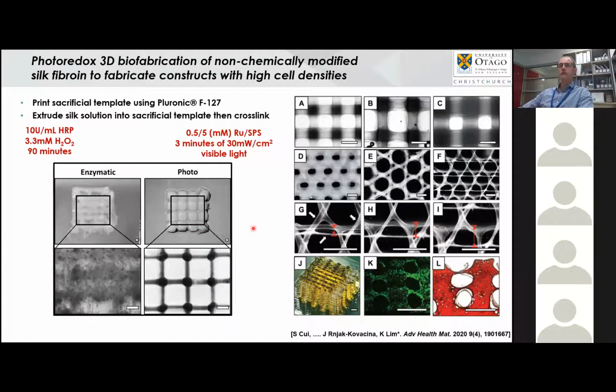And we find that if in this case we're doing a 3D bioprinting process using sacrificial printing, we can end up with silk constructs which have high resolution features we can incorporate cells into, and we're trying to take into account the capability of these visible light cross-linking mechanisms.